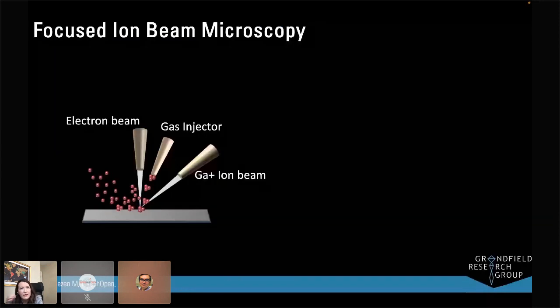And here's where we use something called focused ion beam microscopy. It's like a scanning electron microscope, but instead of just having an electron beam for imaging, we have a gallium ion beam where we can insert ions and mill material away inside the microscope.